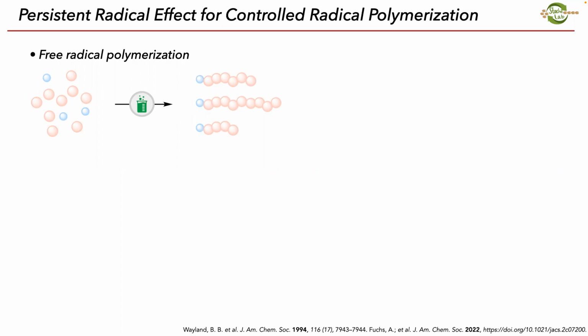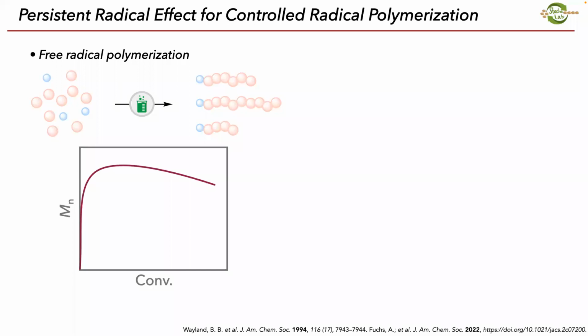But we don't get uniform growth. And so the molecular weight, or the Mn, will increase very quickly, but not consistently with the monomer as it's being consumed. And so what this means is that we don't have control of molecular weight. These chains are all different sorts of lengths, which is going to change their polymer properties. And so this method doesn't give us a lot of control over the polymer at the end of synthesis.